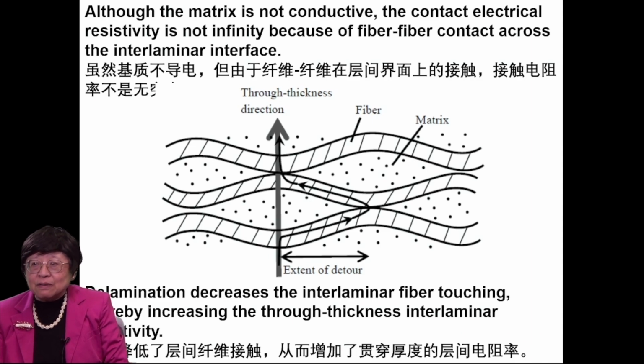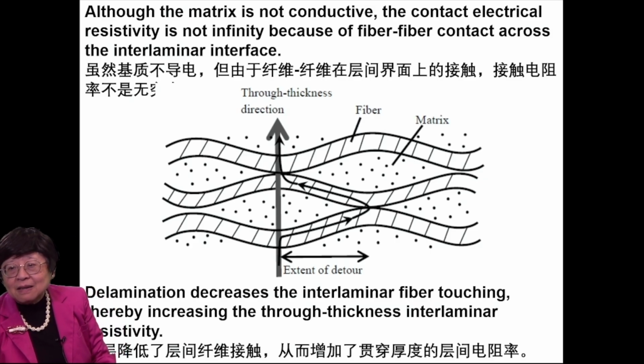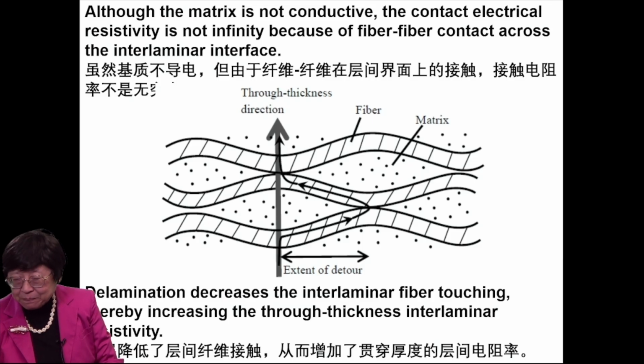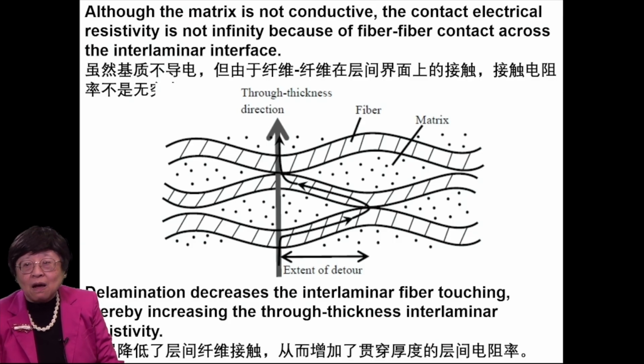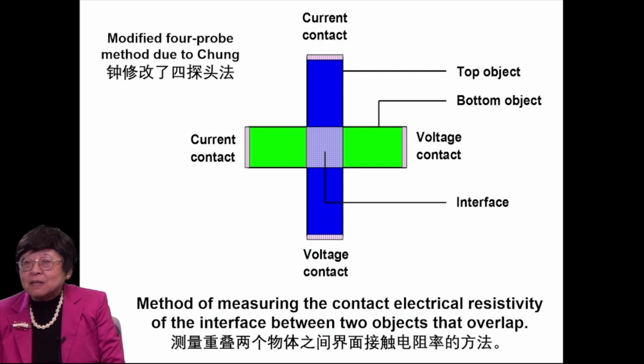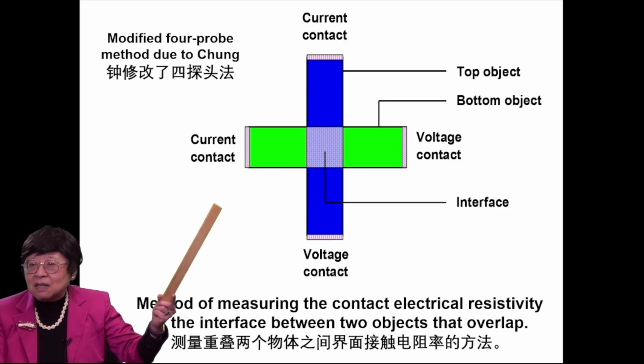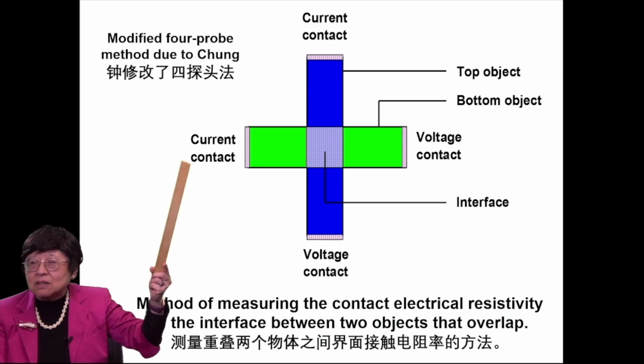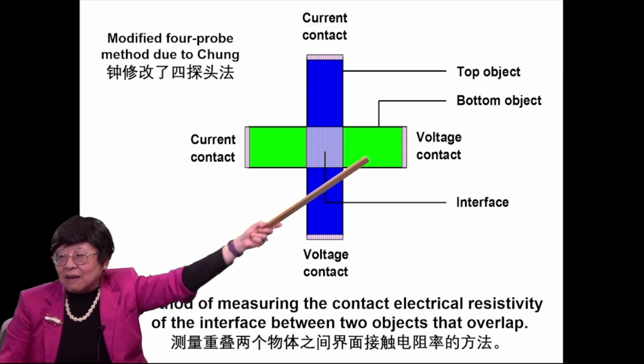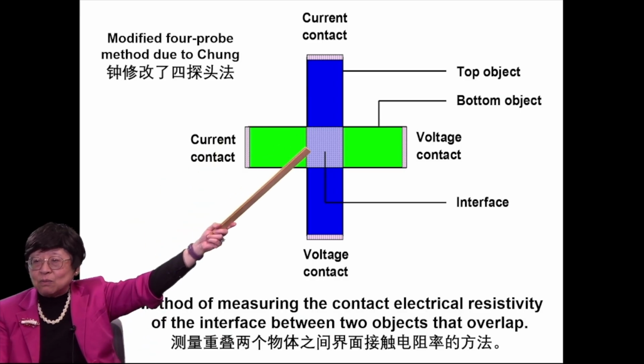Although the matrix is not conductive, the contact electrical resistivity is not infinity because of the fiber-fiber contact across that interlaminar interface. Delamination obviously decreases the interlaminar fiber touching, and so it increases the through-thickness interlaminar resistivity. So the interlaminar interface resistivity is very sensitive to delamination or degradation of the interlaminar interface. I developed a modified four-probe method for measuring the contact resistivity of the interlaminar interface, or for the interface between two objects in general. These are the two objects in the two colors. I used two current contacts here and there, and two voltage contacts here and there. And these two objects have an interface, which is the square junction.